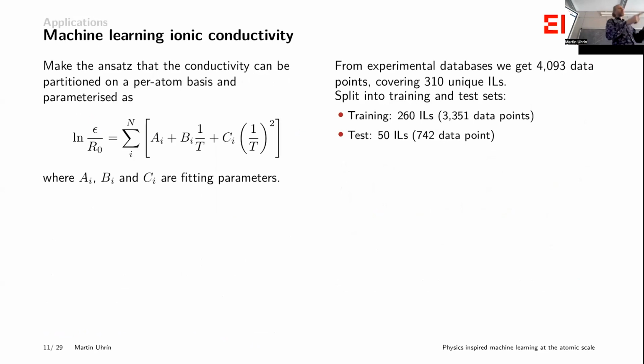There's good data, reasonably high quality from experiments, about 4,000 data points that give us effectively the ionic liquid, what it is, the temperature that the experiment was conducted at, and the measured or inferred ionic conductivity, let's say. So as we always do, I'll split this into a data set. Now, in order to be fair, I didn't want to be simultaneously learning across different ionic liquids and temperatures, because the temperature relationship is a bit easier. So I'm going to split it by the ionic liquid type, so which pair of anion and cation I have.